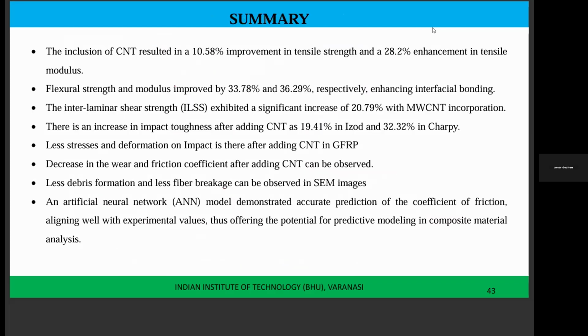So in summary, you can see that there is an enhancement in the tensile strength as well as the modulus, and also flexural strength and modulus can be increased for the mixed coated multi-wall CNT particle-based polymer composite material.